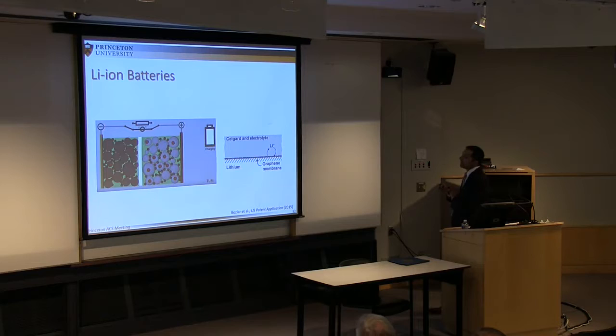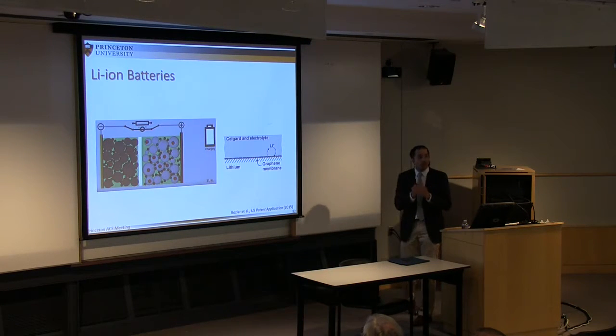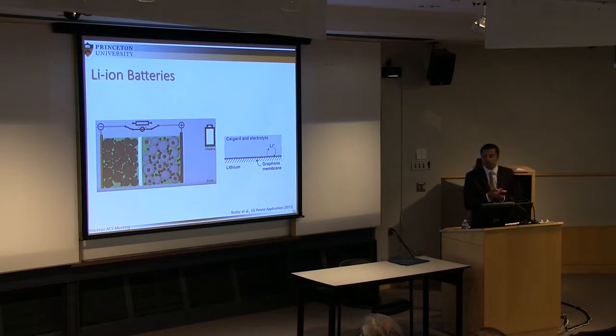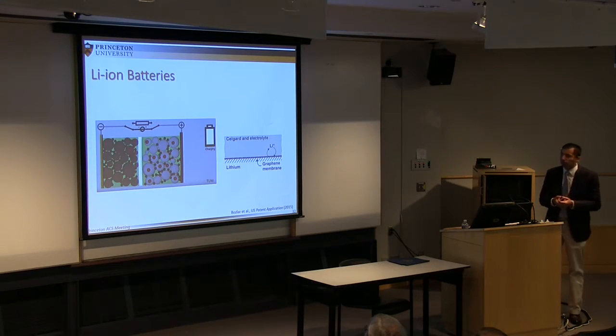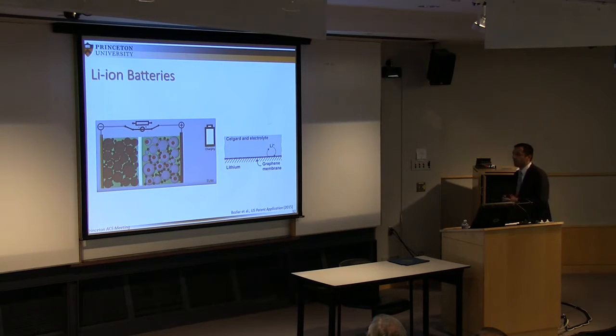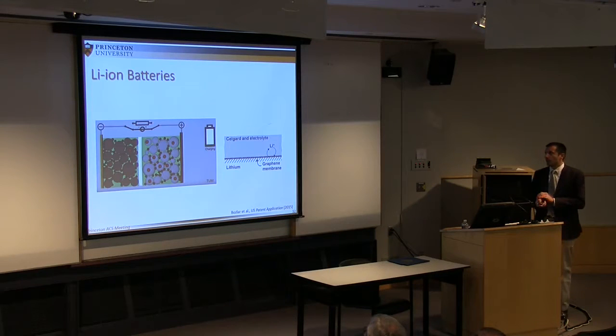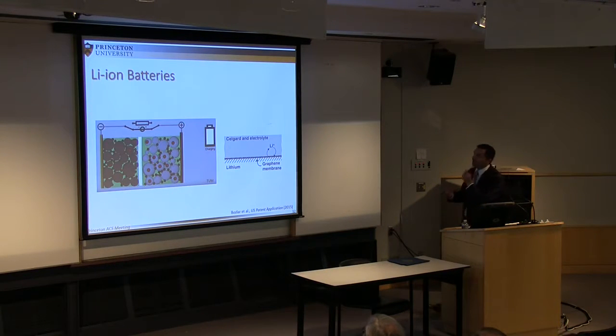Now, if you take a lithium metal electrode as the anode, you have side reactions that take place as you are charging and discharging your battery, and as a result, you have a limited lifetime of your battery. Why? Because you grow dendrites that can pierce through the insulator and short your cell. That's not good. Another type of reaction is that the lithium metal electrode reacts with your electrolyte and forms porous lithium. That's not good either, because it increases the overall resistance of your system.